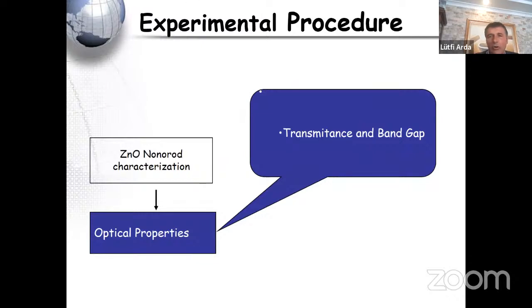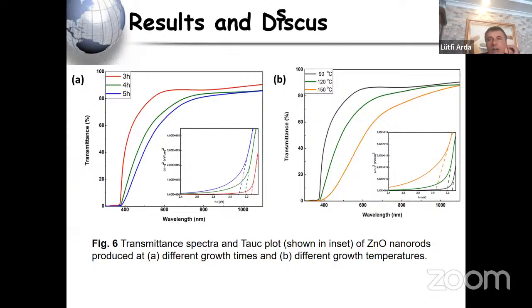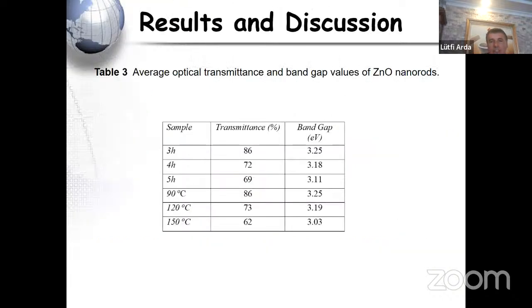For the optical properties, the optical transmittance spectra of zinc oxide nanorods are given in these two figures. As can be seen from the figures, all the samples exhibit high transmittance in the visible region and low transmittance in the ultraviolet region, which is a typical property of zinc oxide. The values of average optical transmission I will give you in the next slide. This is the transmittance and the band gap of the samples.